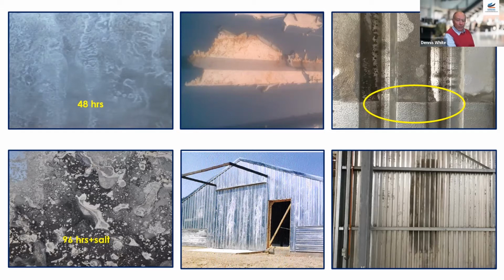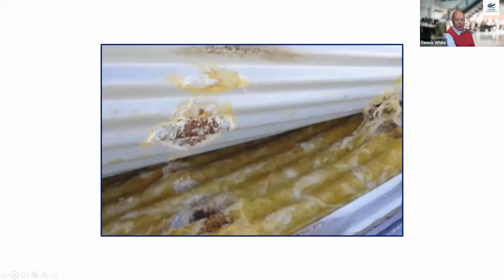And another problem, which is not always obvious, is that the insulation blankets, if they get wet and you try and install cladding over them whilst they're still saturated, actually react with the cladding. And if we look at the next slide, there's an example of where metal cladding was installed directly over a blanket, and you can see the type of corrosion attack on the undersurface of the cladding, which of course won't manifest itself for 8 months to 18 months, depending on the environment and the temperature and the degree of wetness.